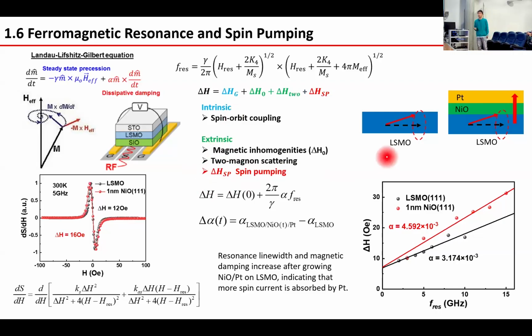So we prepare two samples for comparison, the single LSMO and also the nickel oxide and platinum deposited on the single LSMO layer. In this case, we can extract the magnetic damping from the linear equation, and the increase of the magnetic damping, or delta alpha, relative to the single LSMO reference layer is an indicator of the spin current transferred through the nickel oxide and absorbed by the platinum. So in our case, we measured the magnetic damping of the three-layer sample, where the damping clearly increased compared with the single LSMO layer. So it indicates that the spin current is absorbed by the platinum.